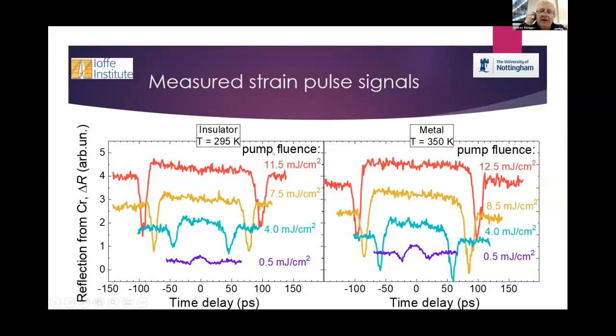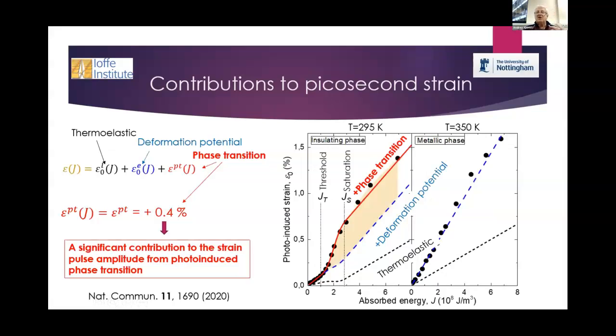Now, these are examples of experiments done at room temperature, when it is insulator, and at elevated temperature, when it is metal. We show that we can measure the time between the first peak and second peak quite precisely, and from that we know the strain amplitude. So we plot this strain as a function of absorbed energy in the vanadium dioxide film. The most interesting things happen when it is initially in the insulating phase: at first we see a linear increase, and then we reach the threshold of the phase transition.